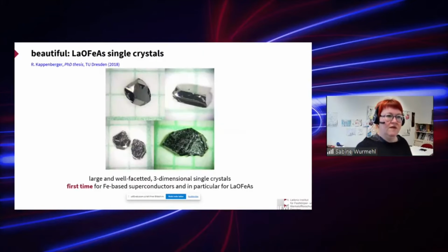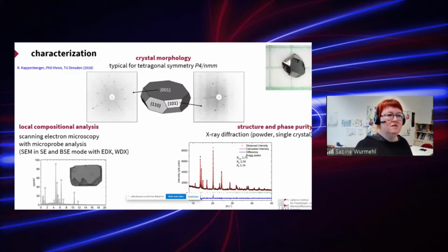And with that, we get really large, three-dimensional and faceted single crystals of the 1111 materials. Of course, we did a very careful characterization of the crystal morphology using Laue diffractometry. You can see here the spots on different facets of our crystals.